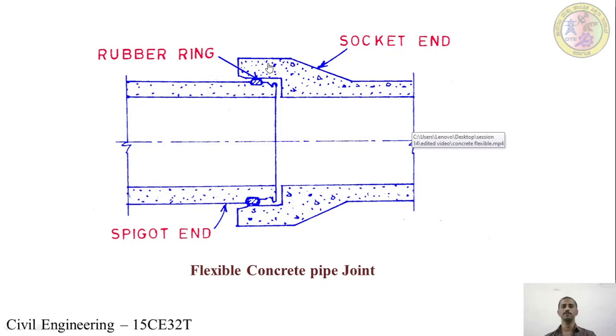You can see here, this is the socket end, enlarged one, and this is the spigot end. The rubber ring is inserted at the end of the spigot in this notch, and the socket end is lubricated properly on the inside. The spigot end along with the rubber ring is slowly inserted into the socket end, and the rubber ring moves from the notch to the groove here. Also, the normal thickness of the rubber ring reduces to its 60% thickness, making sure this joint is watertight. And also, it is a flexible type, allows relative movement between the pipes to certain extent.